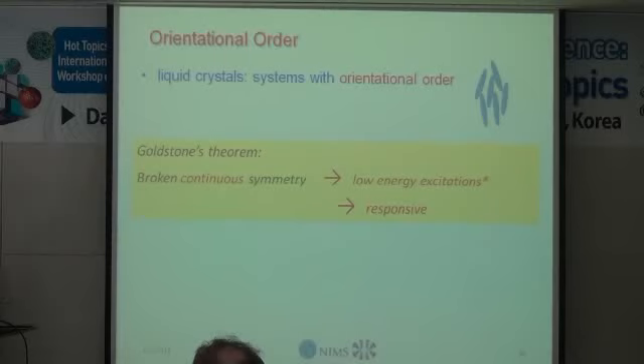So broken continuous symmetry means that the broken symmetry phase, that is a liquid crystalline phase, is continuous. If you take an isotropic fluid and you cool it down, the direction of average orientation can be in any direction, so that's a continuous broken symmetry. And because of these Goldstone modes, these materials are very soft, that is, they're very responsive to almost any kind of stimuli.